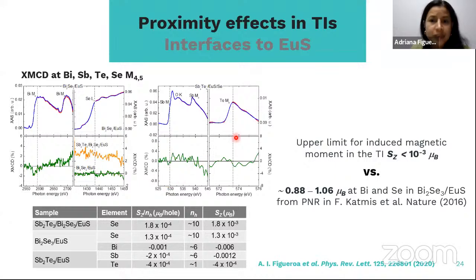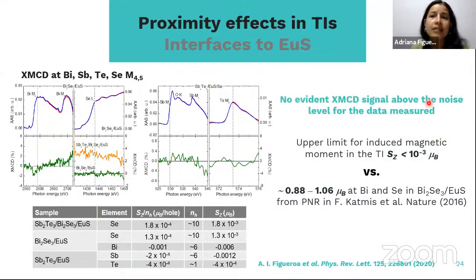And now the main result is whether there was an induced magnetic moment on the non-magnetic atoms of the TI. So we tune the energy to the non-magnetic atoms, so bismuth, antimony, tellurium, and selenium, which are the atoms of the topological insulator layer. And then we try to measure XMCD on those systems, but we didn't see anything. So there is no evident XMCD signal above the noise level for the data measured.